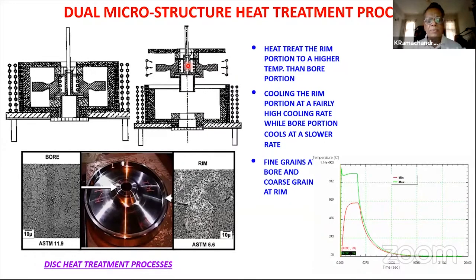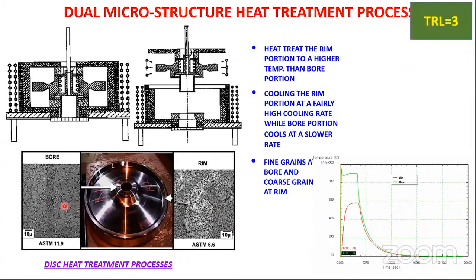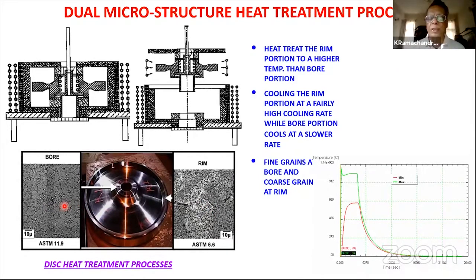And when you finish the heat treatment process, you will see, astonishingly, the rim has a very large grain size, maybe 45 to 50 microns, whereas the bore has a very small grain size, which is good because the large grain size of the rim gives you good creep properties. And the very fine grain at the bore becomes very good in terms of fatigue properties. And you expect about 20 to 30% increase in the life of the part. You don't have to throw it out as soon as one of them is reached. You make them reach the limit at almost the same time, and 30% augmentation in the life of the part is possible.